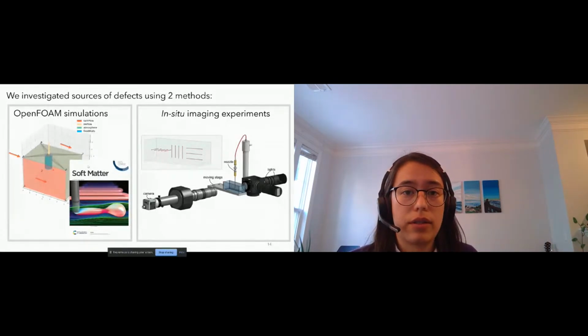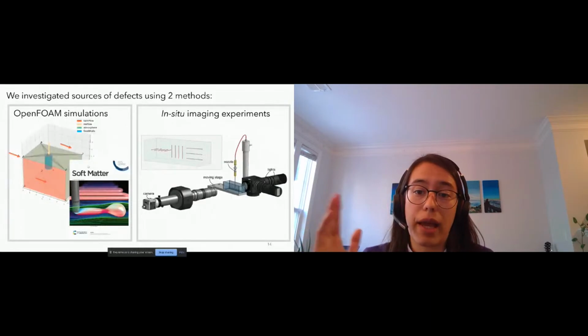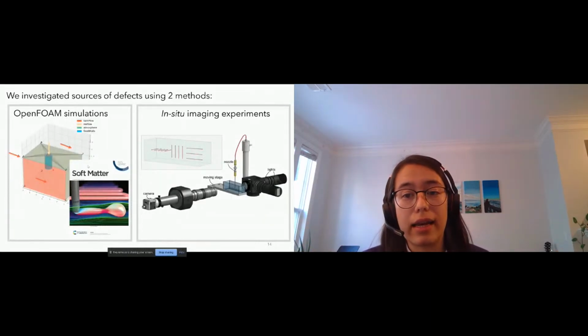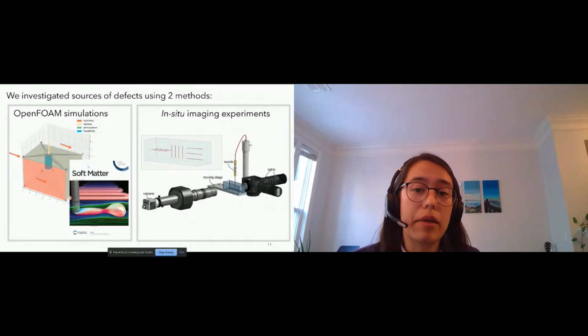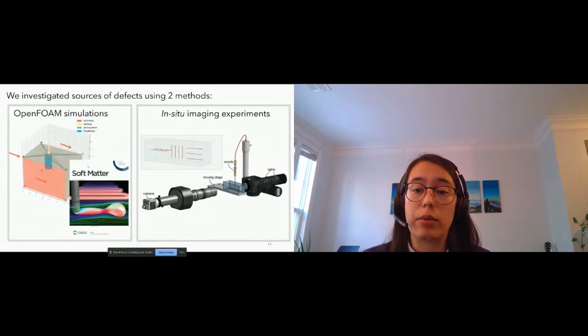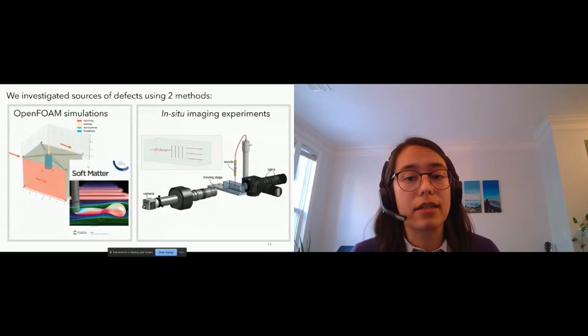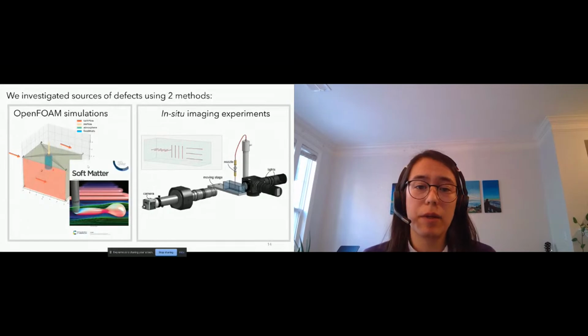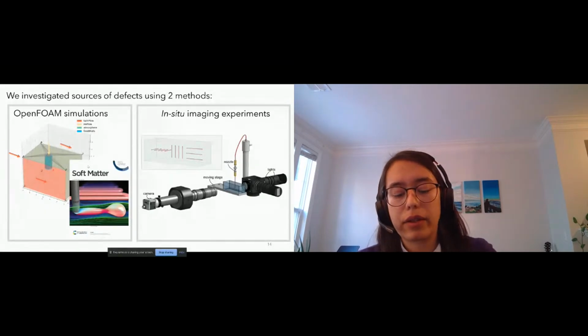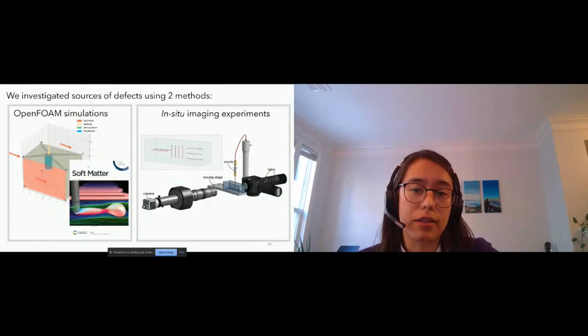We also used in situ imaging experiments. So again, we have a static nozzle and a moving bath, but this time we have a camera looking at the tip of the nozzle so that we can see what's happening as we're printing. And then once the print is over, we can remove the nozzle and go back and take images of our print. So for these experiments, we printed straight lines where we looked at the lines head on to identify their cross-sectional shape and printed them out from the side to look at their lengths.